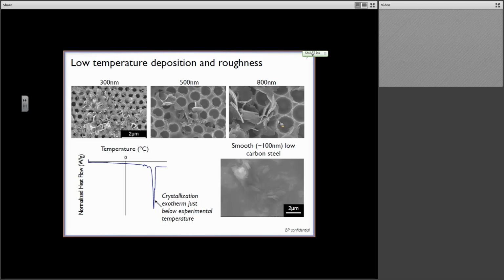What I'm showing you here are some of our deterministic structures with different length scales. The smaller ones over here have these little plate-like deposits on them, and these plate-like deposits are about the same size as the voids that they are sitting on. As we increase the length scale of our surface, the platelets also grow, and at the larger scale we see even larger ones. They're all at the same magnification, right? It's quite interesting here. It suggests that whatever's happening in the solution in this particular case is further influenced by the surface morphology. It's quite clear at the smaller scale that the surface morphology somehow limits the relative growth. I'll show you a schematic on the next slide.